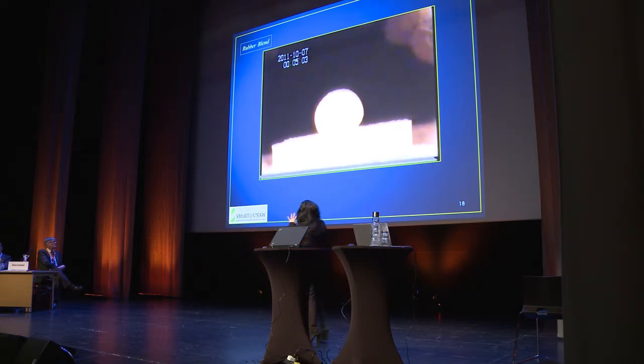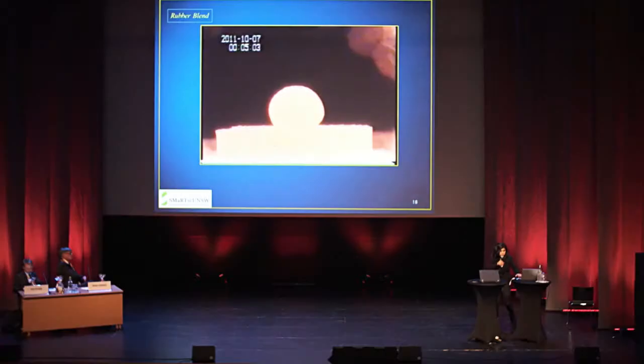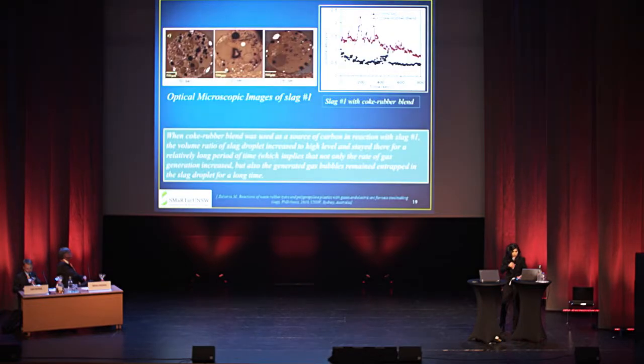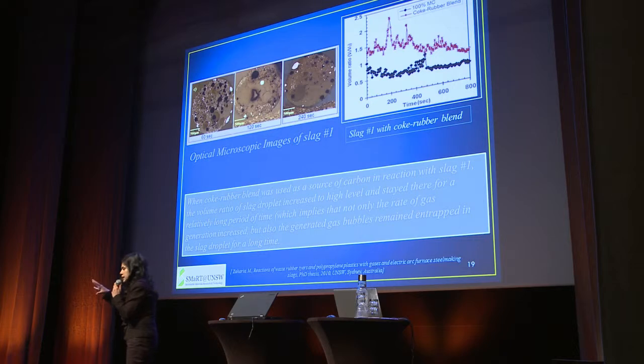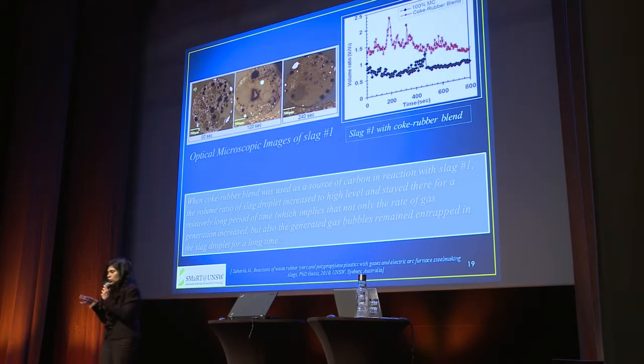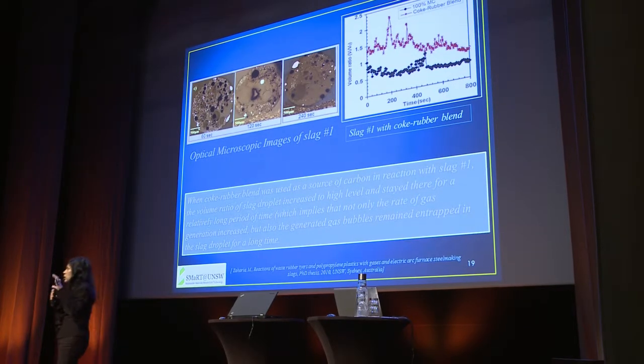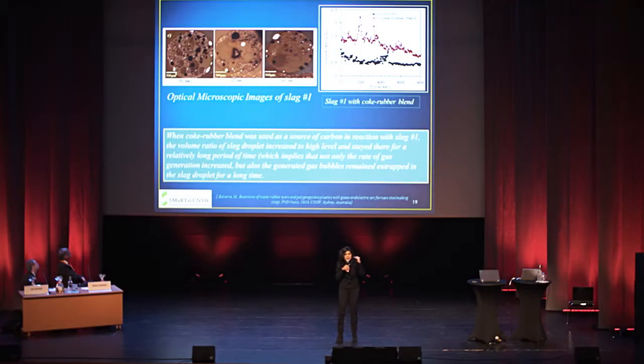If we start to recognize these types of new opportunities, we can do so much more with our manufacturing processes. I'll just take only a moment to show you some of these results that we've obtained in the labs. You can see on the graph that you've got metallurgical coke, which is indicated with that black line, and you've got basically a blend of rubber and coke as shown with the red, and that's just basically showing how the volume, when you actually use a rubber blend, is maintaining itself at a much higher level, and that's exactly what we see in terms of our furnace performance.